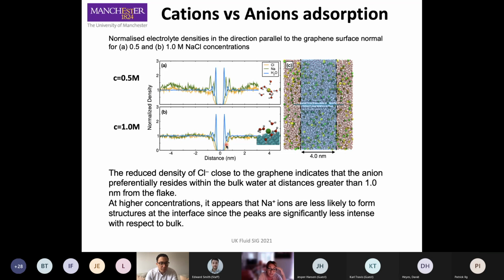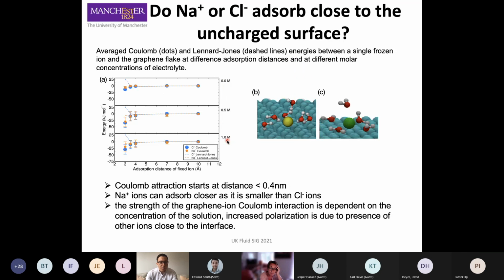It was also interesting that if you increase the concentration of the electrolyte, you can see that the cations, so the sodium, actually, so the peak decreases, so there is less cation in the proximity of the surface if you have a higher concentration of the electrolyte, and this we think is due to probably ion correlation effect. So we didn't expect, to be honest, these results. We thought that the sodium was actually going to dehydrate, so we tried to figure out what's going on.